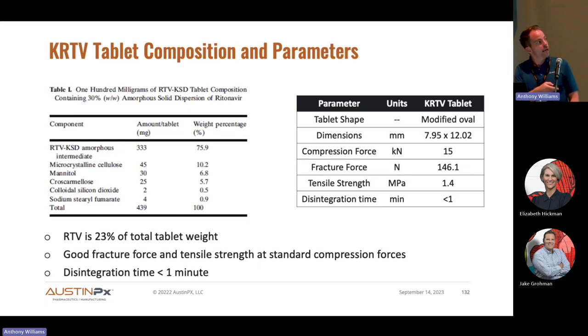So we aim to do the same here, increase the drug load in the amorphous intermediate, then increase the amorphous dispersion load in the tablet so that you can make something more amenable to fixed dose combinations or co-administration of ritonavir with other antivirals. So we were able to generate a 33% drug load KinetiSol intermediate with equivalent performance to Norvir by pivoting polymers. So the commercial product is in copovidone, which isn't a great parachute for ritonavir. We were able to pivot over to HPMCAS, and what enabled that, ritonavir and HPMCAS are incompatible.